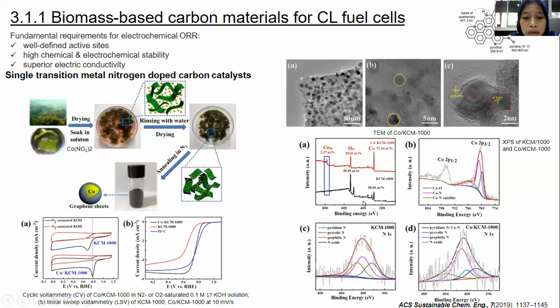Okay, from the LSV testing, from the CV in 0.1 molar KOH, it was confirmed that the as-synthesized product has the characteristic of electrocatalytic sensitivity for ORR under alkaline environment.